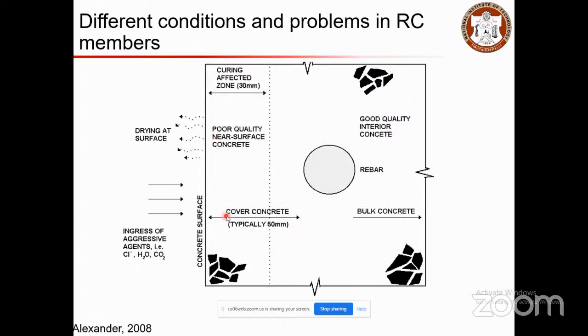So the covercrete will typically be poor quality near-surface concrete, and that is why we give a lot of emphasis on curing. You need to provide adequate curing, so that the evaporation will be from the water that you provide to cure your concrete, not from the concrete itself. If concrete loses its moisture, it is going to affect the strength gain and the durability also. So that becomes the curing affected zone if the curing is not done properly, right? And then this is going to become poor quality near-surface concrete, and eventually that will lead to a lot of issues to the rebar.